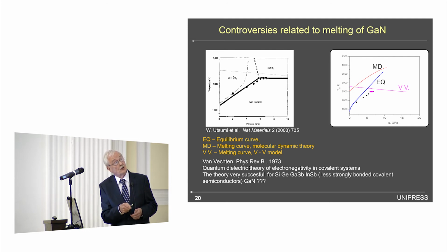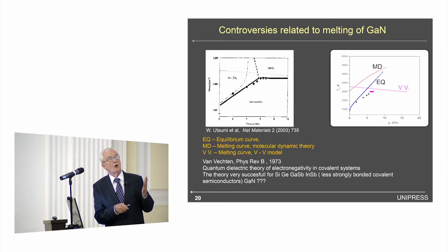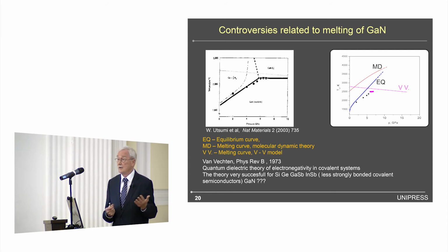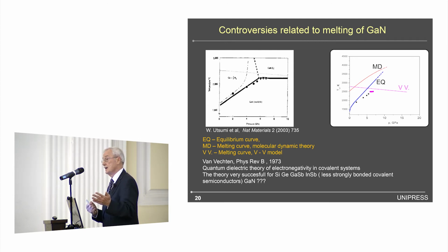And in this picture we put all our information about melting. So we have Van Vechten's theory. This was the first one. We have the molecular dynamics calculation by Harafuji. The theories contradict each other. That's our equilibrium curve. And these are the data of Utsumi. As you can see, the melting which he observed here confirms Van Vechten's theory. And at this point, this result was accepted as a reference. In all publications, you find this data as a reference point for gallium nitride.